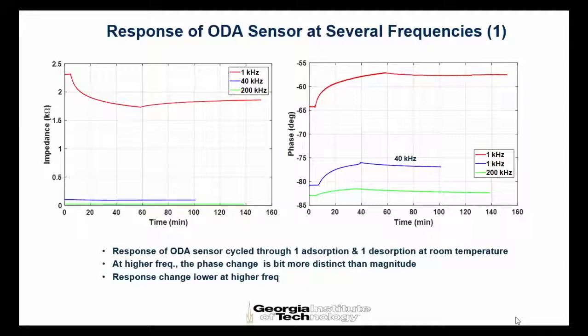We did just one adsorption cycle and one desorption cycle, at room temperature. We didn't increase the temperature, so the desorption is very, very slow, but it's okay. We ran the experiment. And what we found is that at higher frequencies, the change in the response is smaller than at lower frequencies. At this point, we don't fully understand the physics of this, but we can use frequency also potentially as a parameter.